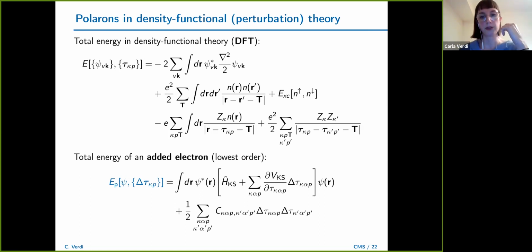The other approximation that we make is that we expand the total energy in terms of the atomic displacement. As you know, once you add an electron, the atoms can displace. And so we assume that the displacements are small enough that we can expand the total energy, and we stop at the lowest order that admits a non-trivial solution. So this is it. This is the total energy of the added electron. This is with respect to the total energy of the ideal crystal, so it's not written here, this term.